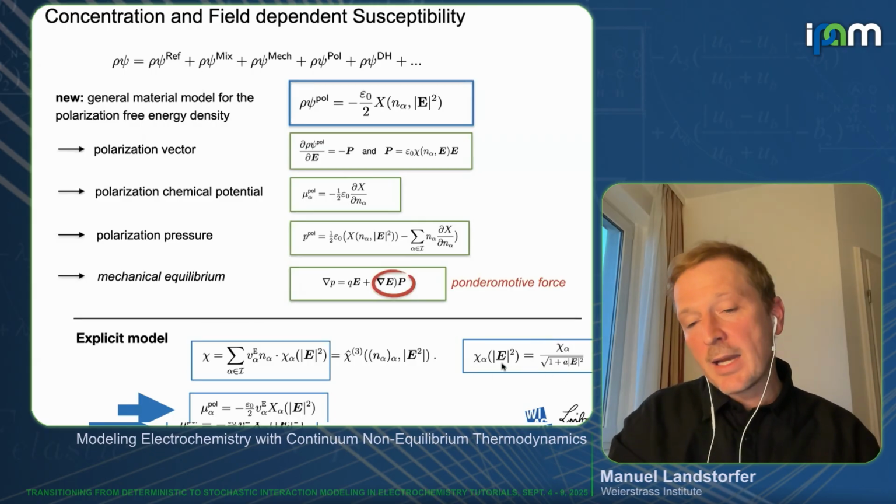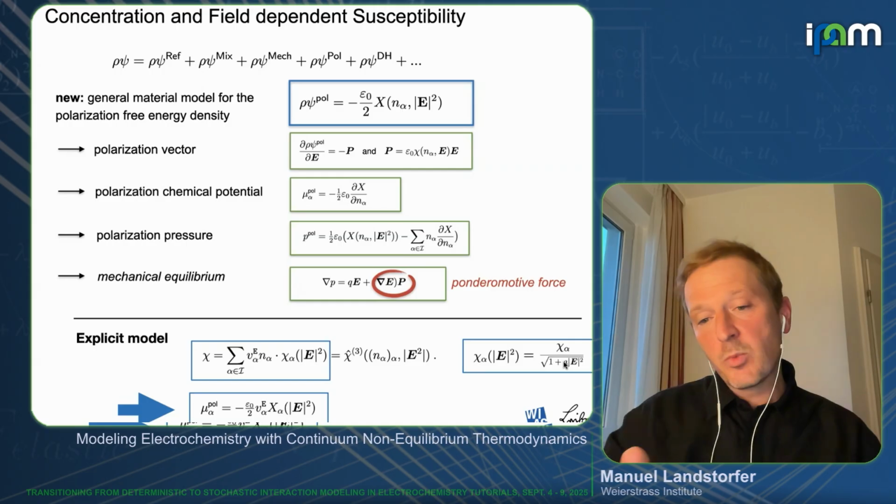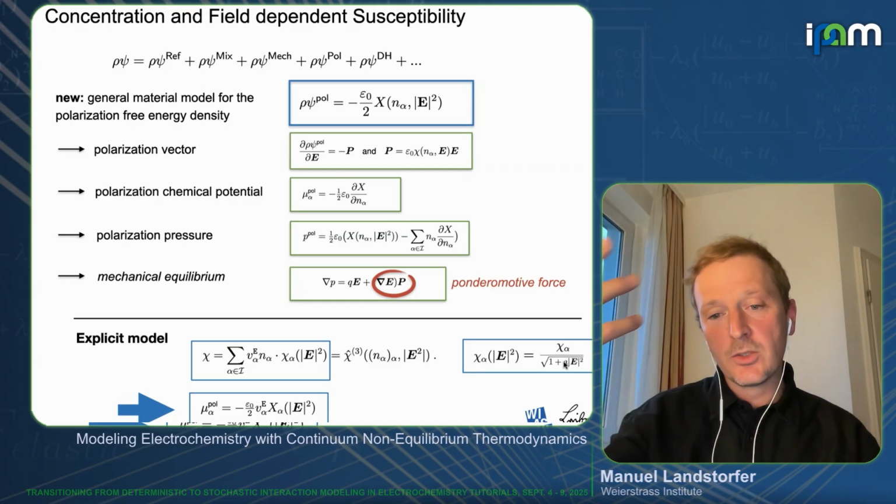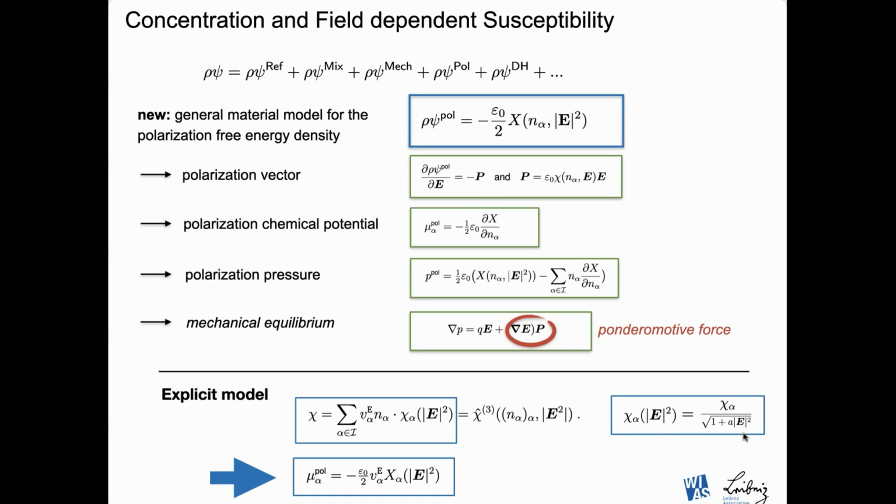But just keep in mind that whenever you increase the electric field, you decrease the dielectric constant. This is why it has this shape. And why does it have an E field squared? Because when you build the partial derivative with respect to the electric field, you have to get out a vector again. So from vector calculus, it's clear why you have an E squared dependency.